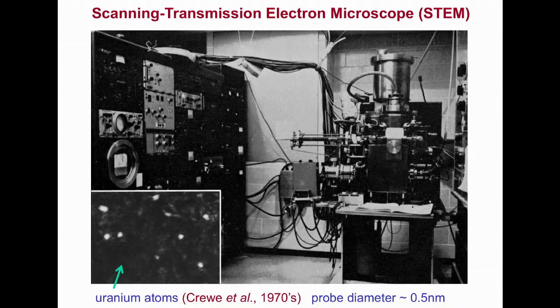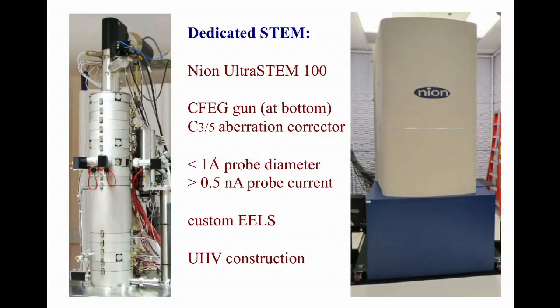In fact, aberration correction is not essential for seeing atoms, as was shown in the 1970s by Albert Crewe, who imaged heavy atoms that were dispersed on a thin carbon film. He used a scanning transmission electron microscope, which scans a finely focused probe of electrons across the specimen and records the image serially as a function of time. The resolution of a STEM is determined mainly by the electron probe diameter, which was several atoms wide in Crewe's instrument, but small enough to resolve atoms when they are widely separated. Crewe's design used a field emission electron source, whose small source diameter makes it easier to form a sub-nanometer probe.